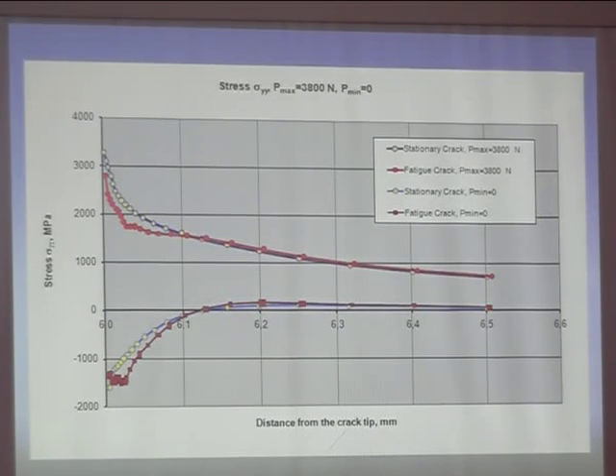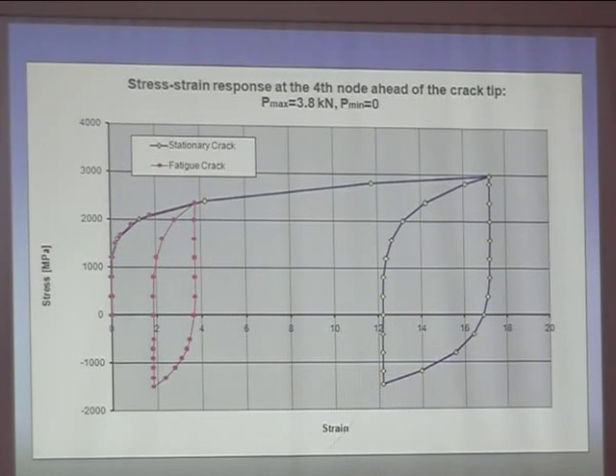But you see, this is only finite element. It doesn't need to be necessarily 100% true, but it qualitatively gives the picture. So what I did next, I said, let's go to a point ahead of the crack tip and see what the stress-strain response is. I chose the fourth node in order to be away from that first element, which was corrupted so much because of huge rotation and deformation. So this is the hysteresis loop for the fatigue crack, and this is the hysteresis loop for the stationary crack. Again, it shows that the minima here are not much different, but the maximum does change.